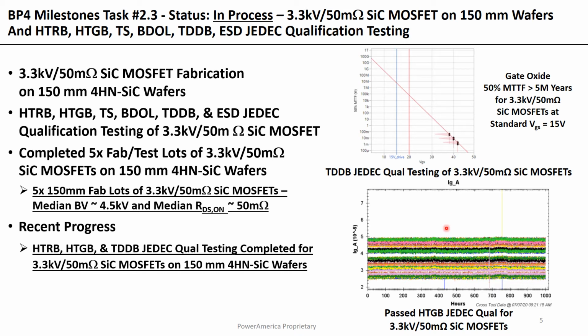Down below, you see the in situ high temperature gate bias JEDEC qualification testing results for these 3.3 kV 50 milliohm silicon carbide MOSFETs. We used three fabrication lots with 25 devices per lot for 1,000 hours of HTGB JEDEC qualification testing, and that passed successfully. Not shown, but we completed successfully 3 qualification lots, 25 devices per lot, of high temperature reverse bias JEDEC qualification for these 3.3 kV 50 milliohm silicon carbide MOSFETs.